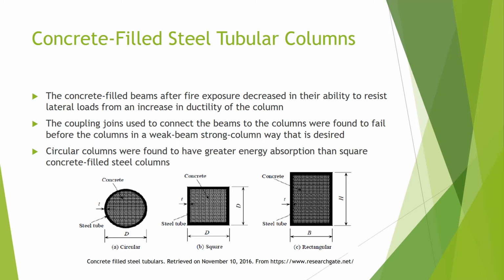The concrete-filled beams after fire exposure decreased in their ability to resist lateral loads from an increase in ductility of the column. The coupling joints used to connect the beams to the columns were found to fail before the columns in a weak beam, strong column way, which is desired. Circular columns were found to have greater energy absorption than square concrete-filled steel columns.